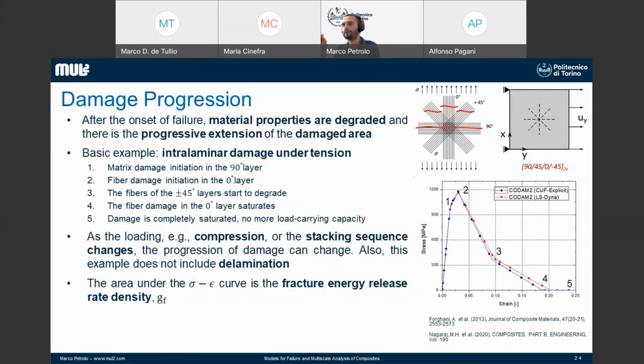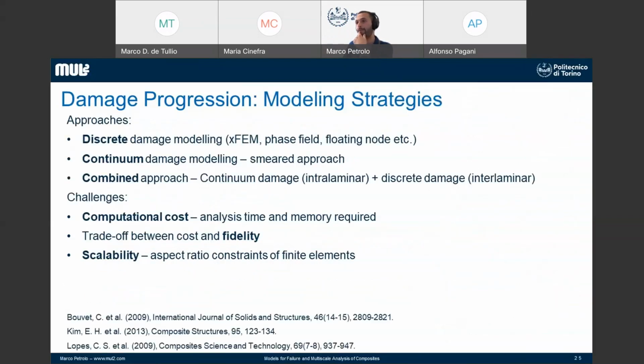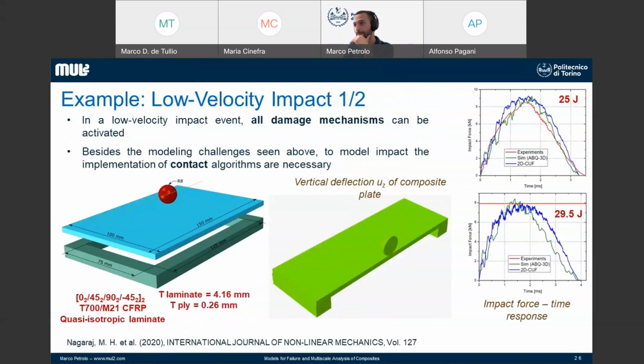Also, the models you have change as soon as you consider different failure mechanisms. So you need a model for compression, you need a model for tension, you need a model for delamination. All this put together makes your damage model very complex to deal with. There are different approaches to deal with this problem. The one that we have in our virtual platform uses a combination of continuum damage for the intralaminar damage, so the damage that occurs in plane in our ply, and discrete modeling to deal with the delamination, so the delamination between different plies. And this is a typical example that you can run with a progressive damage model.